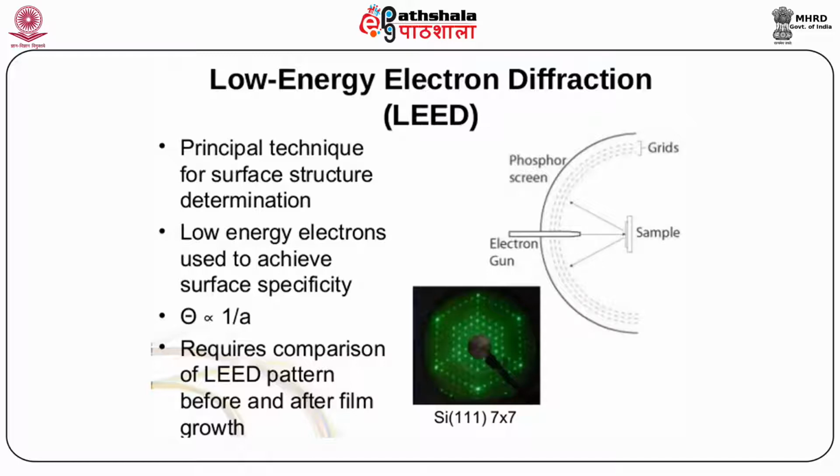Due to the very strong interaction with matter, electrons have a mean free path in the same order as the interatomic space is. By measuring a diffraction pattern for certain energy of incident electrons, a periodicity of surface lattice may be determined by kinematical approach. One of the main assumptions for kinematical approach is that the incident electrons scatter in the crystal just once. This assumption is often not fulfilled, but the kinematical theory describes the diffraction pattern well.